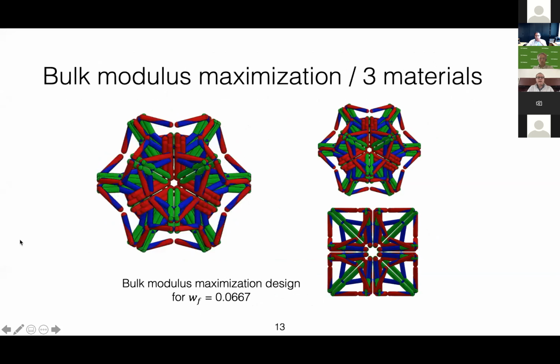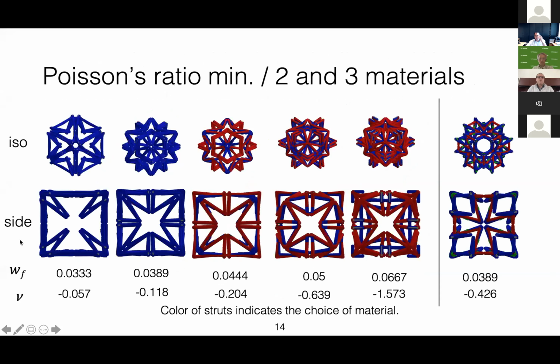We also have an example of Poisson's ratio minimization for 2 and 3 materials. These are the kinds of designs that we get. The 3 material design is the one on the right. In this particular case, it was just more difficult to find a weight fraction constraint that would have 3 materials. But we know that for the same weight fraction, we get a lower Poisson's ratio if we use 3 materials than if we use 2.